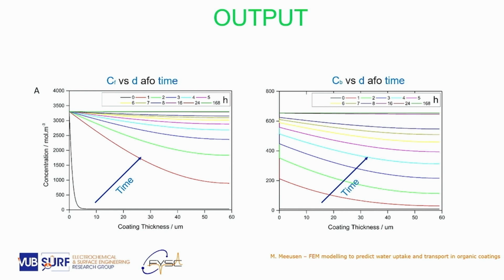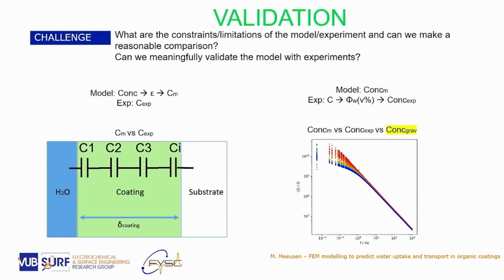And for the validation, we are using our impedance measurements because it is not so easy to have a validation of the electrolyte transport through the coating. So in our finite element model, we take a kind of local capacitors in the coating, and then there are 2 ways. Either out of the finite element model you try to predict what the capacitor value is, or you try to predict the fraction of the water, which is the phi, that I showed you earlier. And the phi you can also calculate out of the impedance measurements.